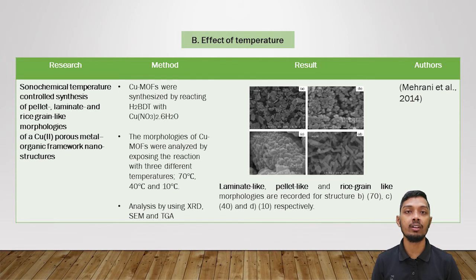For the next one is the effect of temperature. In fact, Mehrani et al. in 2014 reported that copper MOF were constructed by exposing to three different temperatures, which are 70 degrees Celsius, 40 degrees Celsius and also 10 degrees Celsius to study the formation of metal organic framework and also its morphology. This analysis was done by three instruments. The result revealed that each temperature contributes to different morphologies: 70 degrees Celsius results in laminate-like morphology, 40 degrees Celsius produces pellet-like morphology, and 10 degrees Celsius produces rice grain-like morphology.